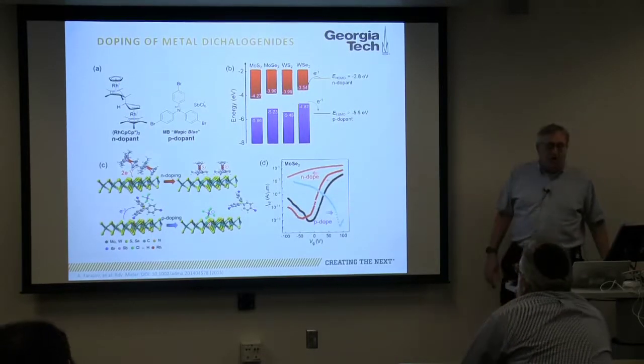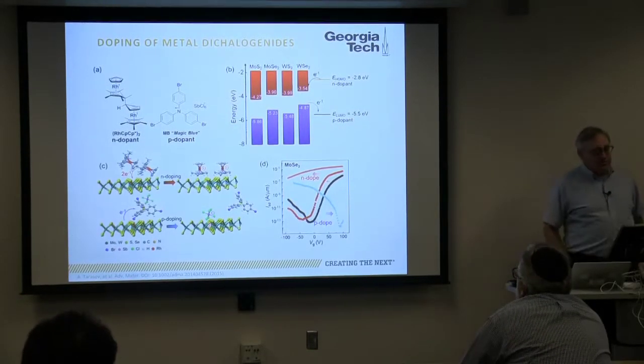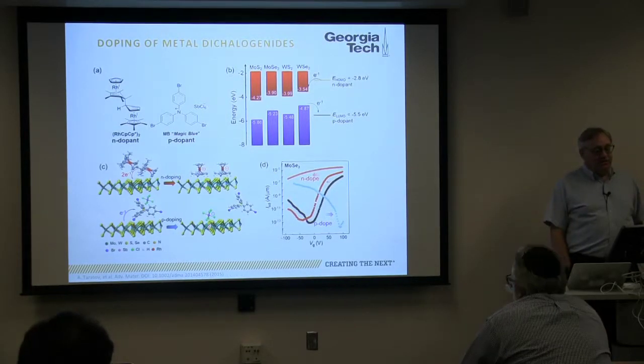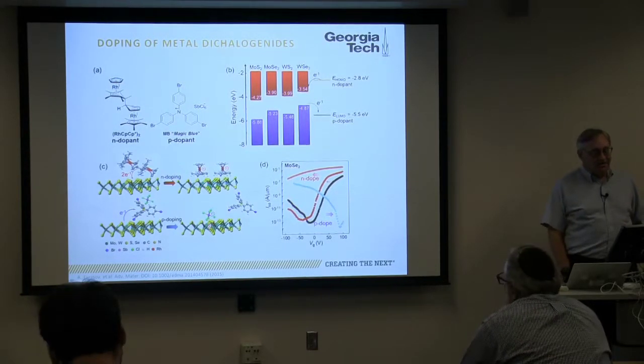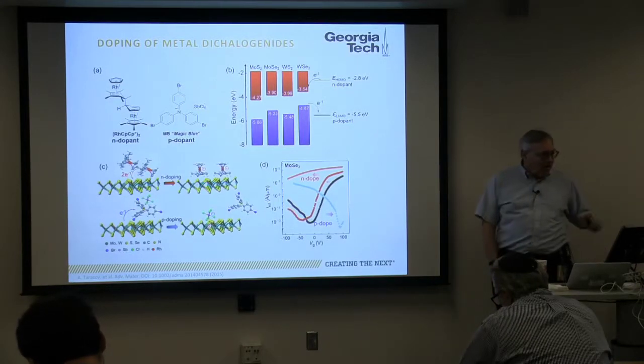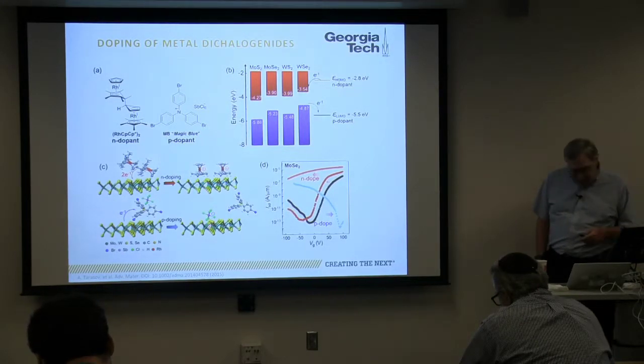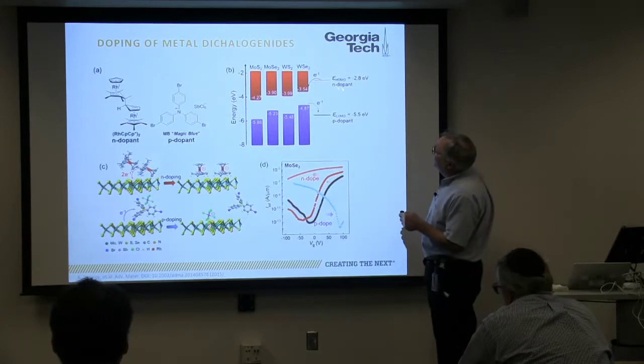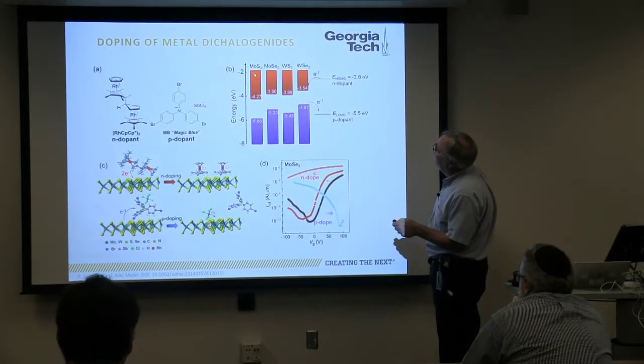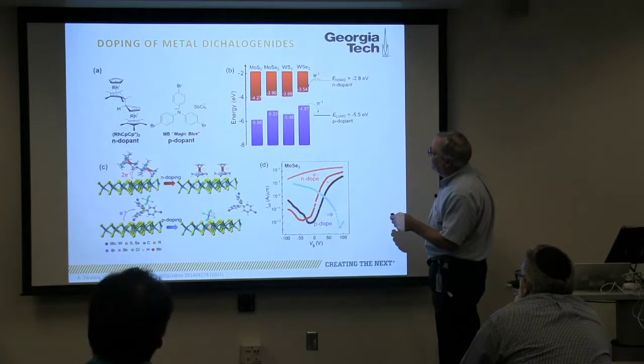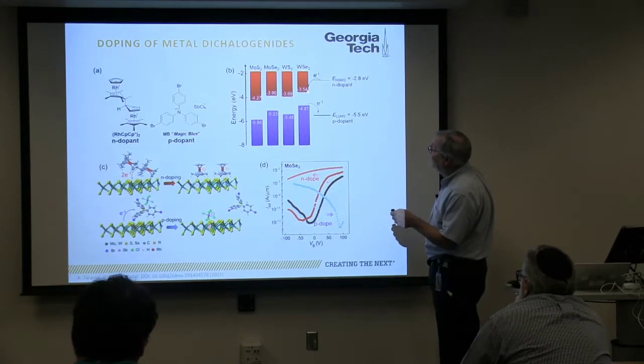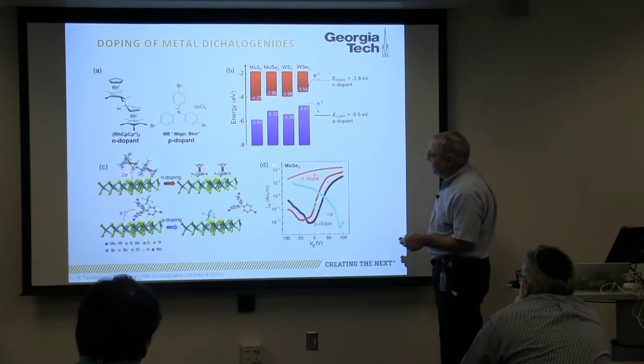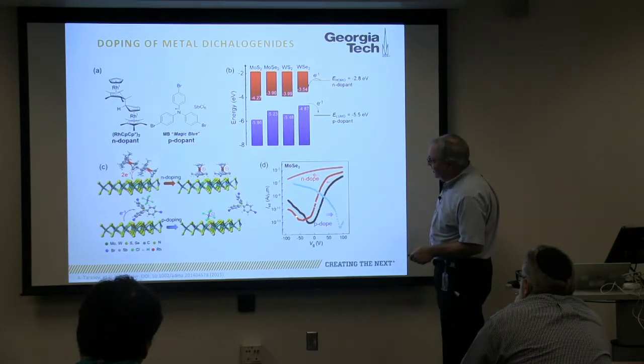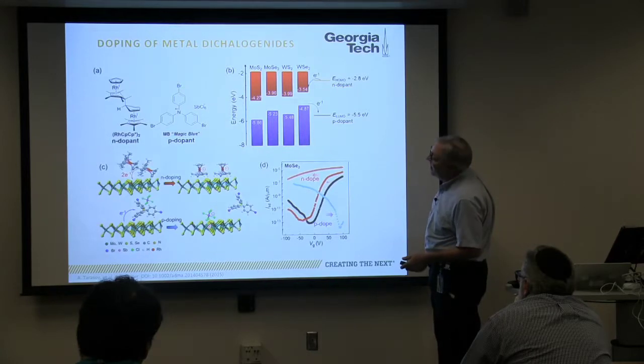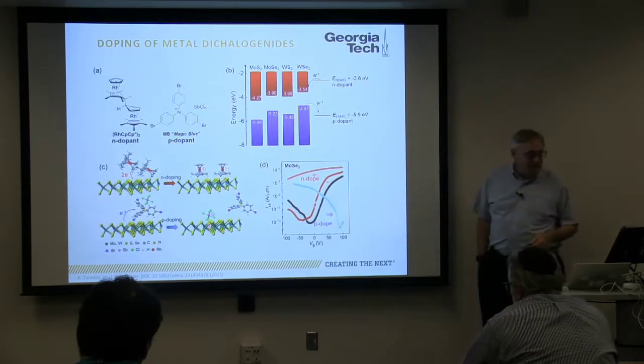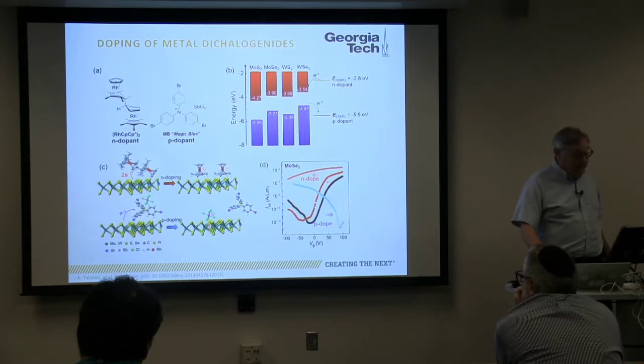Getting a little closer to home, we collaborated with Eric Vogel and examined the doping of moly disulfide, moly diselenide, tungsten disulfide, and tungsten diselenide. And you'll see 2 slides on these materials, or at least one of them. Okay? And so with the n-dopants, we can basically dope the conduction band. With one of these dopants that we have, we can actually, in the case of tungsten diselenide, dope the valence band. And when you do that, you can dramatically shift the transistor characteristics, okay? And you can tune that, okay?